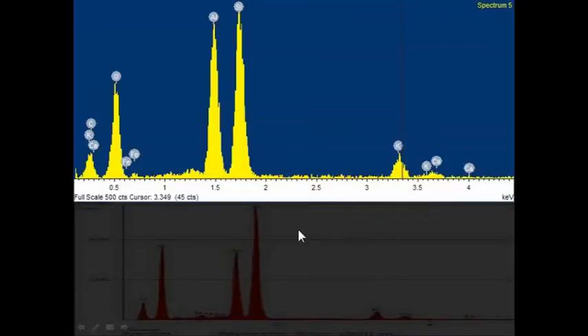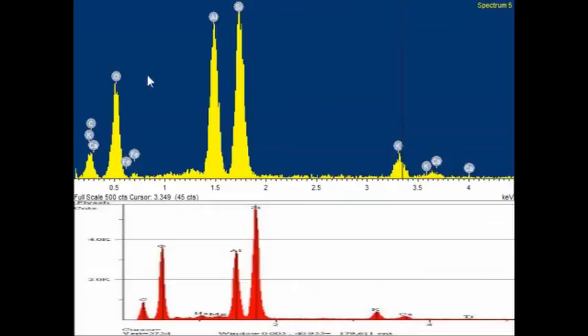So I did an elemental analysis, seeing that it's an aluminum silicate particle. And I was able to go and find a source. The bottom elemental analysis is taken from a corporation who does analysis on coal ash. And I apologize, I had to squish it to get it all onto the same slide, but I wanted to line up the silica peaks, the aluminum peaks, the oxygen peaks, the carbon peaks, so that you can get an idea that what we're seeing in our sample, this upper spectrum, is very much the same specimen as what they analyzed, this known compound here, which is coal ash, fly ash coming from a coal-fired power plant.